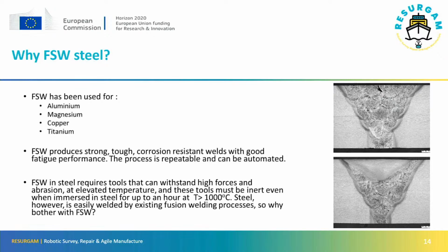After it was developed for aluminium, the process was developed for magnesium, copper and titanium, because those are also regarded as very difficult materials to weld. Friction stir can weld them quite easily. And the welds themselves are strong, they're tough, they're corrosion resistant. You can automate the process and take out the variability, so it's very good. So people said, we want to do that in steel.